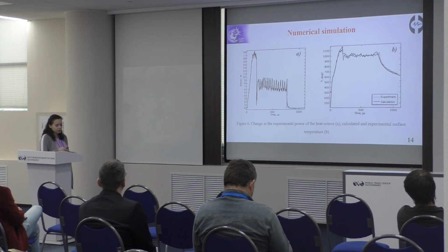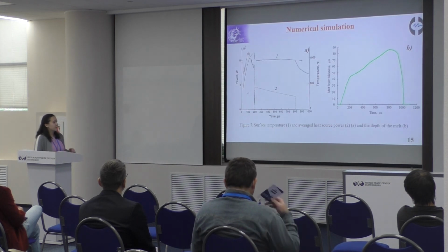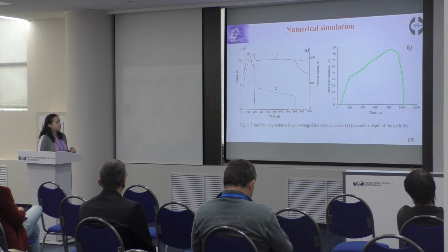But in order to get rid of those pulsations, we decided to take the average power during the pulse, and here you can see the temperature profile that we finally get. We also calculated the depth of melted material, and it reached 80 micrometers.